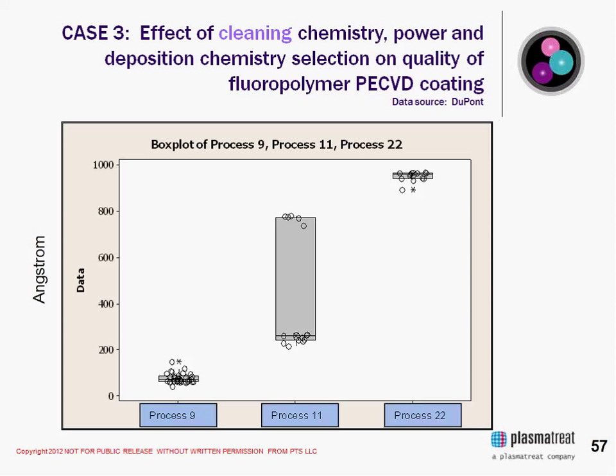And also, what I did not discuss is that the customer looked at the influence of the plasma on the quality of the adhesive bond. So they did two types of aging studies. One of them was looking at the plasma-treated FEP for up to a 6 month or a year period prior to doing the subsequent adhesion step. The other thing they did is they bonded on day one, for example, and they put those in the aging oven as well. And they pulled those out and looked to see if there was any deterioration of the bond because of the plasma-treated surface, and there was none.